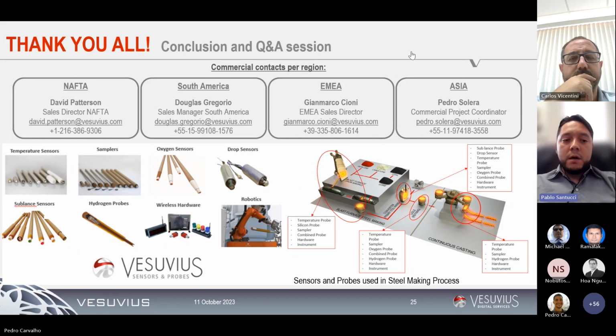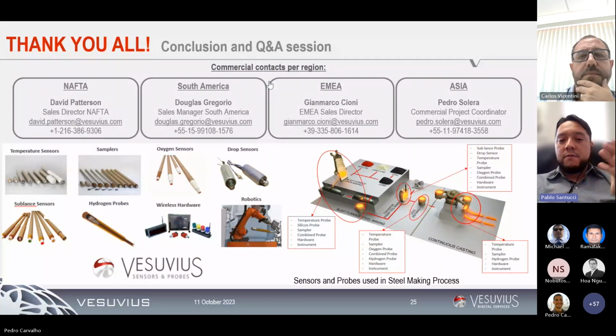And our experience is that we do have good correlation with the pin results. However, as I could see in the past, you can get a calibrated reference from the LECO device, and depending on the range of hydrogen that the customer specifies, the uncertainty of this standard from LECO tends to be higher than 50% of what the customer is running or monitoring. I'll give you some examples.